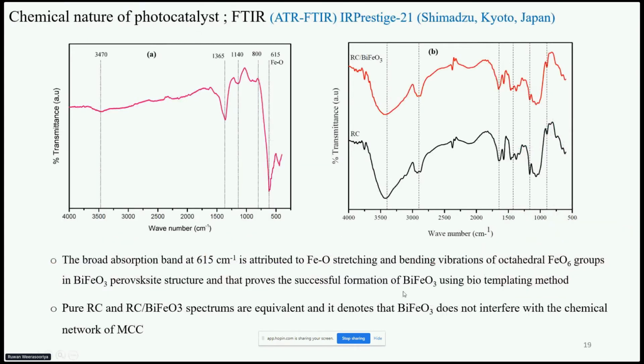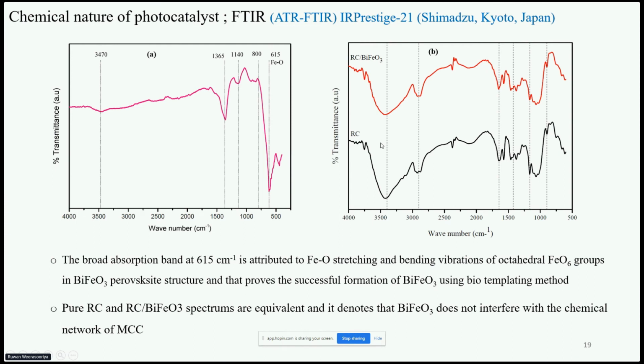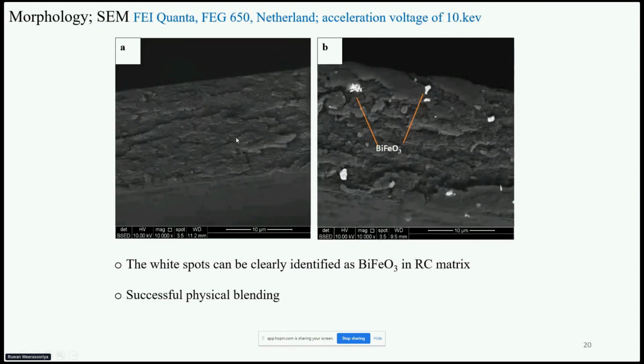In the characterization, this is the FTIR spectrum obtained for bismuth ferrite powder and prepared photocatalytic films. The right side figure shows the FTIR spectrum obtained for pure RC and photocatalytic film. The black curve represents the FTIR spectrum obtained for pure RC, and the red curve represents the FTIR spectrum obtained for the RC bismuth ferrite composite. So according to that, the two FTIR spectra are similar, and therefore it can be confirmed that the incorporation of bismuth ferrite does not interfere with the chemical structure of pure RC. According to morphology, the left side figure is the morphology of pure RC, and the right side figure is the morphology of the photocatalytic film. The white spots are bismuth ferrite particles, and this confirms successful physical blending.